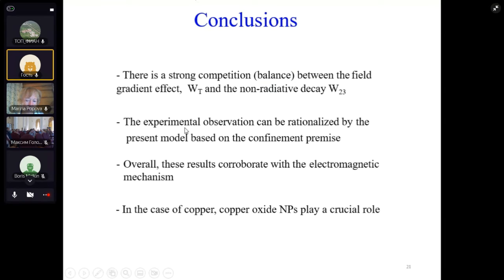And we concluded that the experimental observation can be rationalized by the present model, assuming, as I emphasized above, a confinement of europium complexes that, during the synthesis process, we assume migrate towards the metallic nanoparticle. And the overall result is that we corroborate the so-called electromagnetic mechanism, okay? And in the case of copper oxide, the nanoparticles play a crucial role. It cannot be taken out, okay? So these are the conclusions.